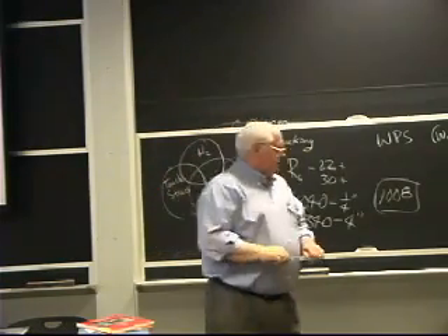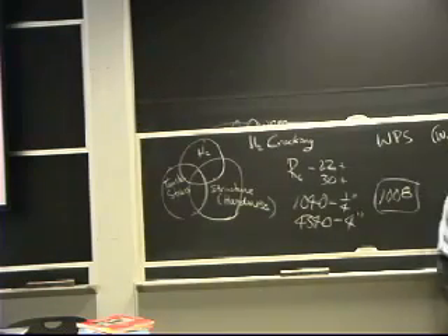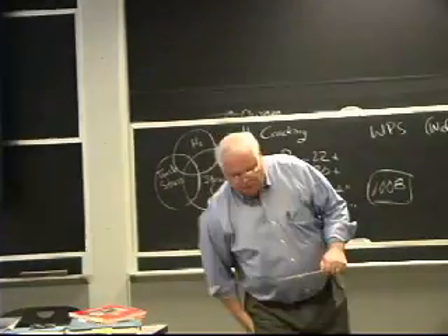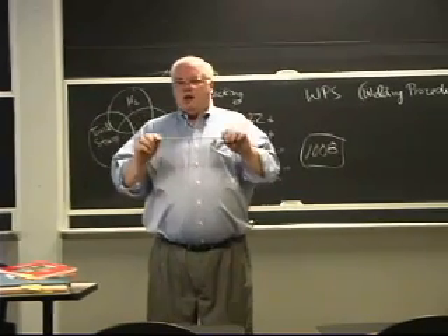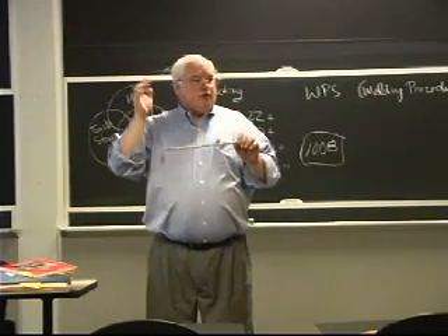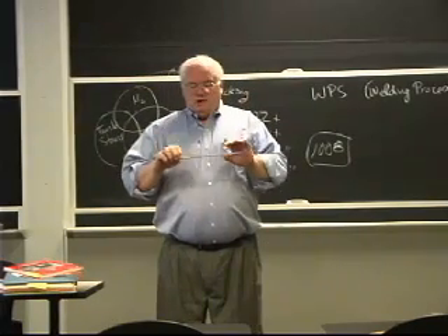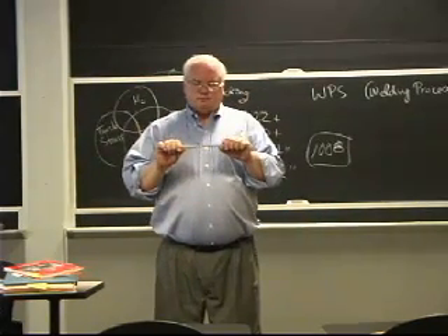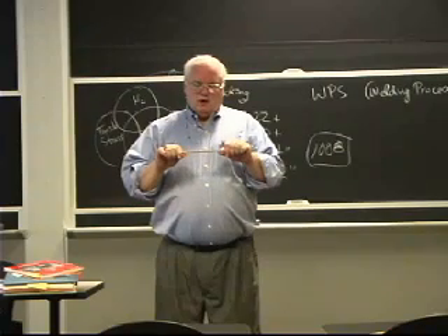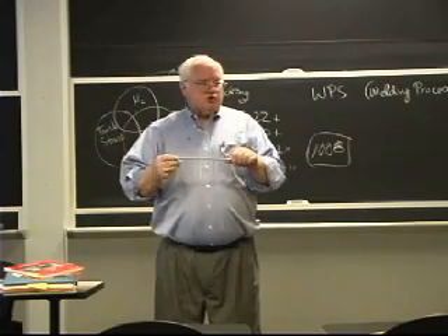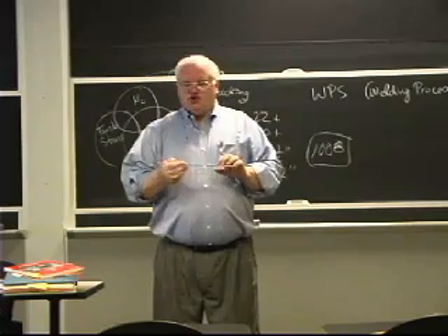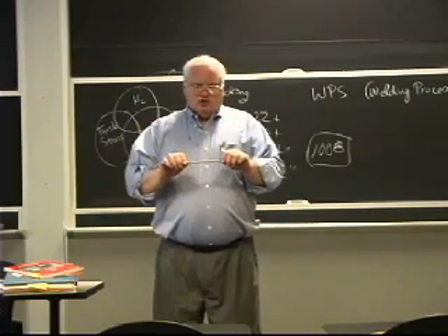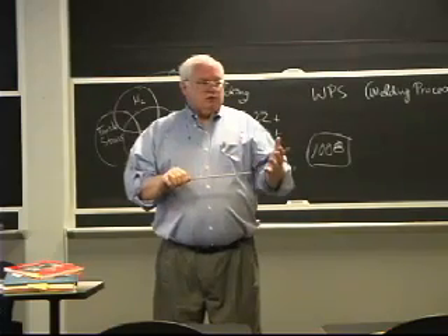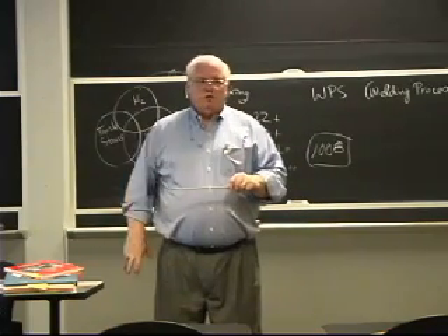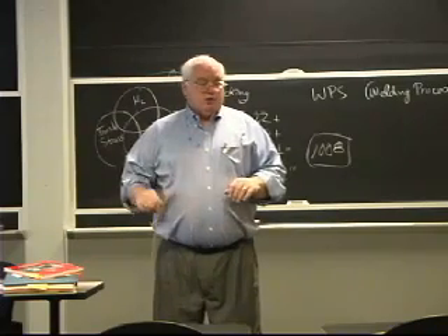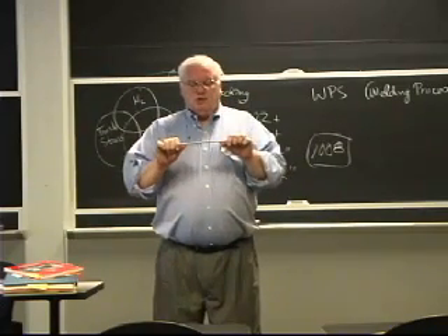Now, this particular flux, and I don't know if you'll be able to see it or not, is mineral coated, and they've done everything they can. They heated this to about 700 degrees to try to drive off all the moisture. And this is the type of electrode that they actually heat up and keep warm, okay? You check these out at the shop, at the fabricating plant, out of the tool room, and they kept them hot in an oven at 200 or 300 degrees. In some cases, they actually give the welder a little portable oven they carry with them with this really critical steel that will crack very easily if it gets any hydrogen.